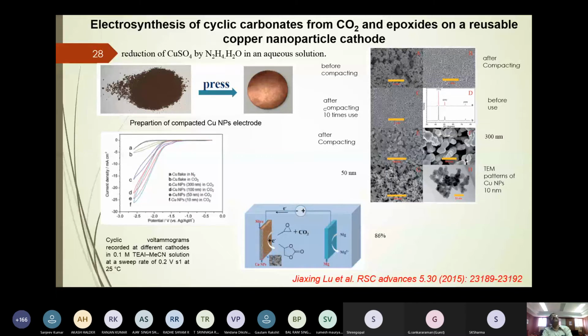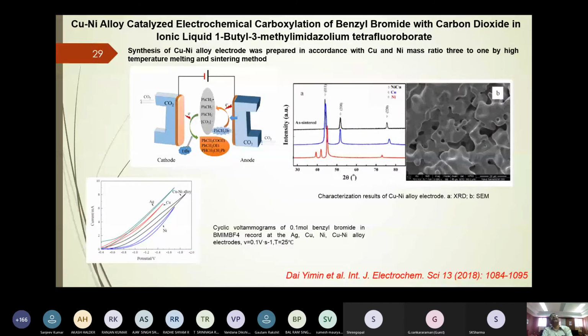Okay, and then CV shows the higher onset potential for the copper nanoparticles in the size of 10 nanometers, and shows high current. This shows that this size gives a higher yield for the conversion of ethylene oxide to ethylene carbonate, or here we can also convert propylene oxide to propylene carbonate with a yield of 86%. Okay, now the next slide shows how the copper nickel alloy without silver behaves for the conversion of